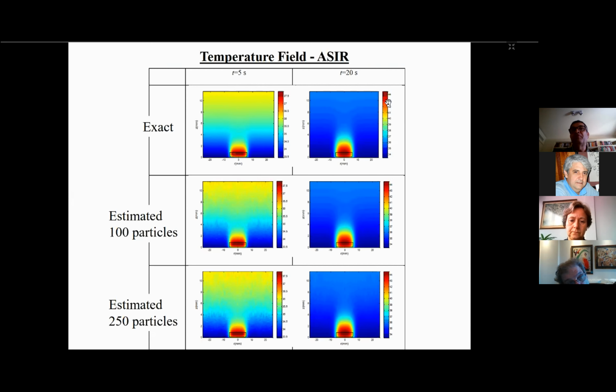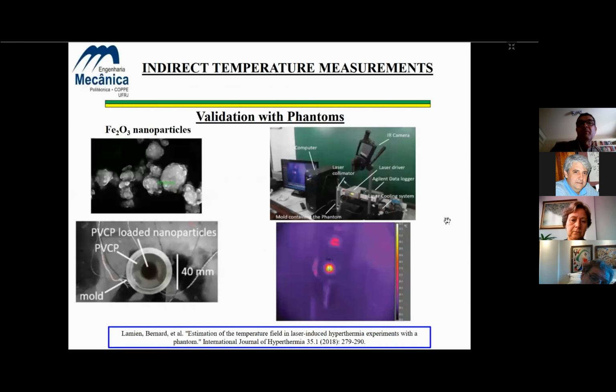These are the exact temperature fields, and this is the tumor region here, and this is the temperature field that is estimated with this particle filter solution. And so these techniques we applied actually to some experiments for validation by using phantoms made of a plastic PVCP. And the phantom contained the region with nanoparticles, in this case, iron oxide nanoparticles that we have produced ourselves, to simulate the tumor. And the phantom is heated by a laser, and the surface temperature measurements are taken with an infrared camera. And in this figure also we can see some thermocouple wires inside the phantom that were used. Some of the measurements were used for the inverse analysis, and the others were used for validation.